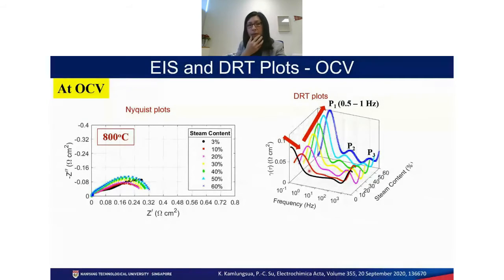That tells us that, we think, there is an activation process: when the moisture content is too low at OCV, the electrode is not fully activated. But when the moisture content gets to 10%, it starts to kick in and the reaction starts to take place. So likely it's due to the surface activation at 10% steam content that kickstarts the electrode reaction.